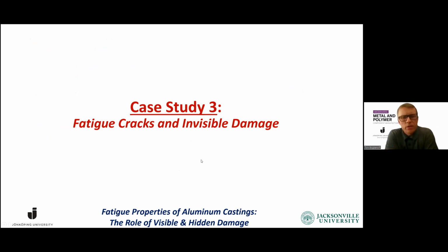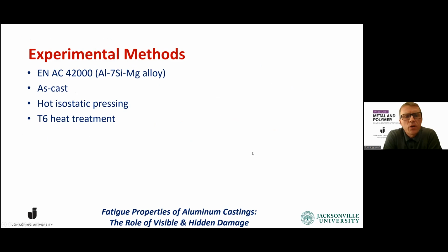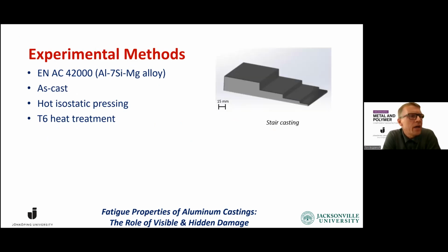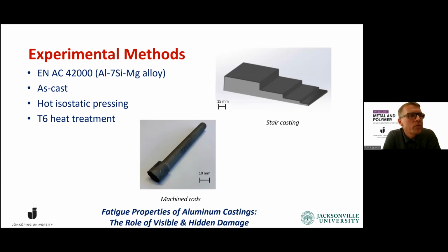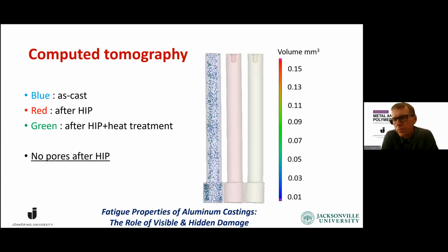Tony. Yes, thank you. Now we will talk about a casting in aluminium, a 42,000 alloy that we casted in a staircase casting. We tested it in the as cast condition. And what we did later was, because we know that we should have porosity in this, we did hot isostatic pressing, hipping to the parts that we machined, and also we did a T6 heat treatment of the material. And to actually validate that we are closing all the porosities, we are doing a CT scanning of the material.